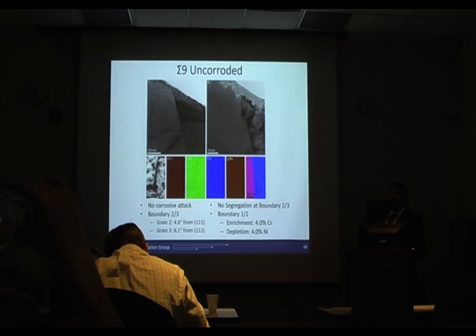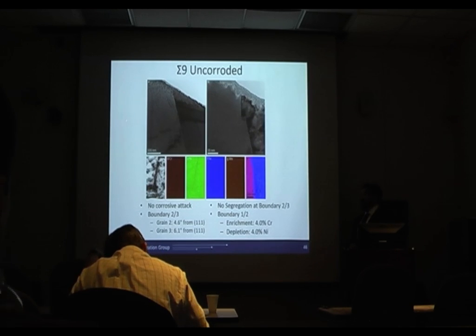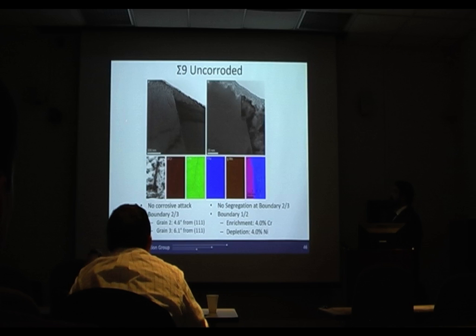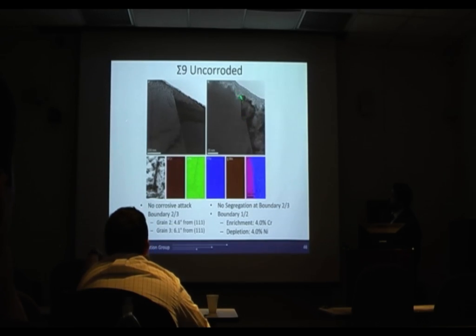However, the sigma 9 that did not corrode was the most interesting of these, and you can see that we have this kind of faceted structure here. It's a little bit difficult to see, but there's also a grain boundary trace, most likely between this point here and the actual surface.